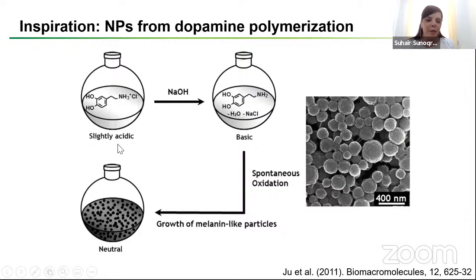And the inspiration came from the famous dopamine. The first study, published in 2011, reported the formation of nanoparticles from dopamine due to the oxidation of the catechol moieties over here in basic conditions, forming these nice looking nanoparticles. So essentially, the catechol compounds, when they undergo oxidation, this makes the phenyl ring over here reactive towards nucleophiles, which initiates a sequence of reactions resulting in the formation of these polymeric or oligomeric structures.